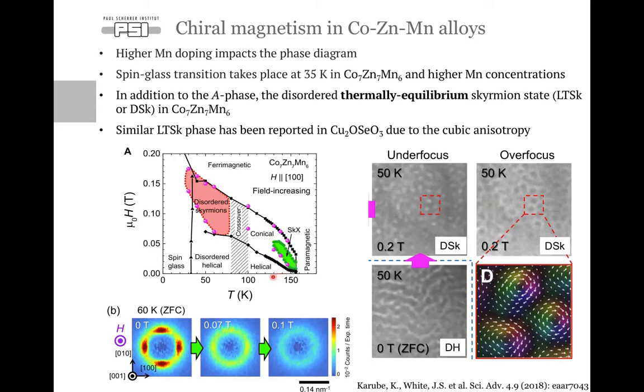But as we go down in temperature, we can stabilize another skyrmion phase at low temperatures that appears at higher magnetic fields and just above the spin glass transition temperature in this material. And this is unique to cobalt zinc manganese 7-7-6, but a similar effect has also been observed in copper oxide selenide, with the difference that there is no spin glass phase at low temperature, and the effect of the additional disordered skyrmion lattice phase is explained by the development of strong cubic anisotropy at low temperatures in this multiferroic cubic chiral magnet.